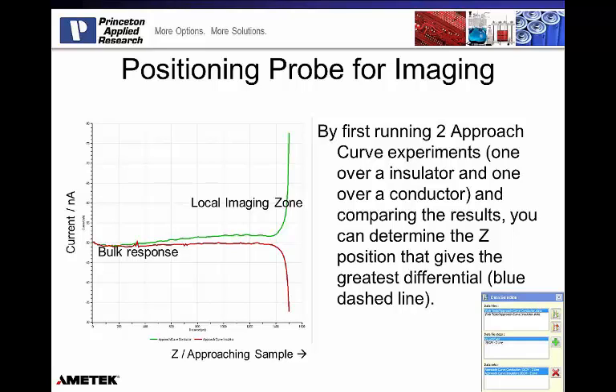If I go back then, I can overlay these two scans, the approach curve over the insulator and the approach curve over the conductor. Let's overlay these responses. We can see both are giving similar type current in the bulk response, and then as the probe increments down and down in Z closer to the sample surface, both of them provide a localized response. But the localized response over the insulator makes the current go down at the tip. The localized response over the conductor makes the current go up at the tip. And so once I overlay these, I know now where to position the probe, and we can even see and kind of predict the impact of probe to sample distance on electrochemical resolution of an SECM experiment.